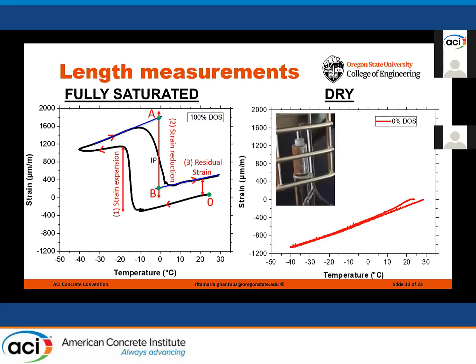Now, if we look at the graph for a sample with a very low degree of saturation, an almost dry sample, we can see that the strain versus the temperature follows a straight line, and that's because of the absence of ice formation.